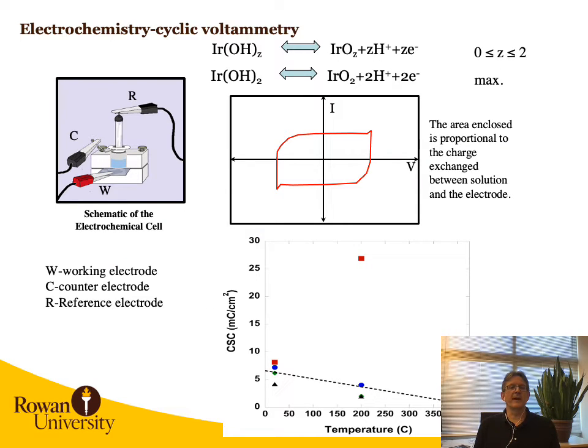Ultimately, what we care about is the performance of these materials electrochemically. So we have an electrochemical cell here. Our coated sample is the working electrode. A platinum coil is our counter electrode, and we have a reference electrode sitting in a phosphate buffered saline solution. We ramp up the voltage and we measure the current, and you expect to see this hysteresis-like behavior.